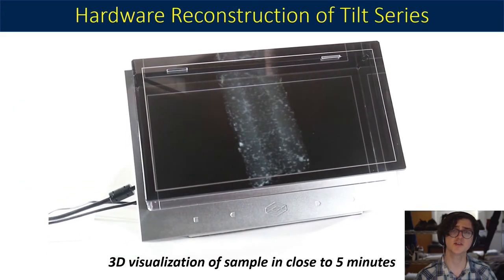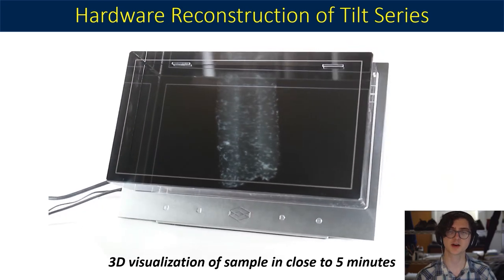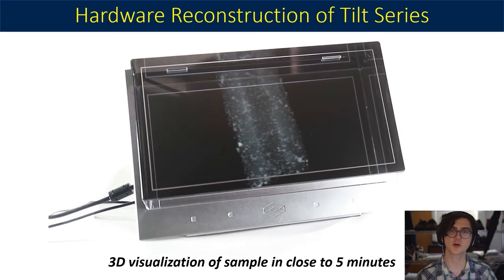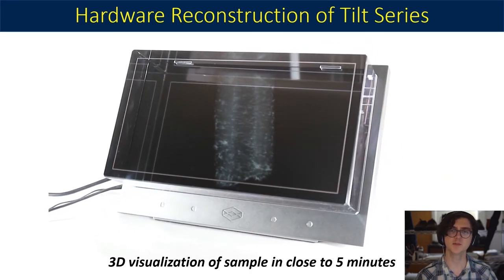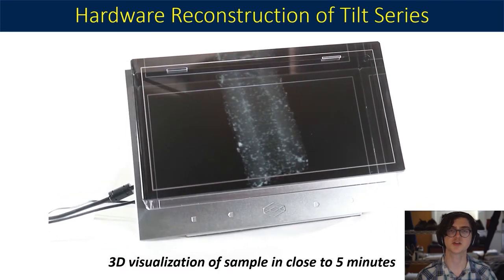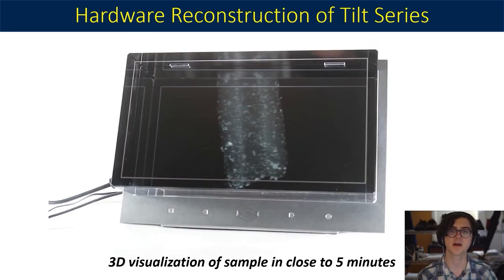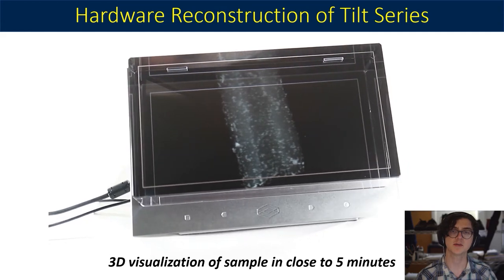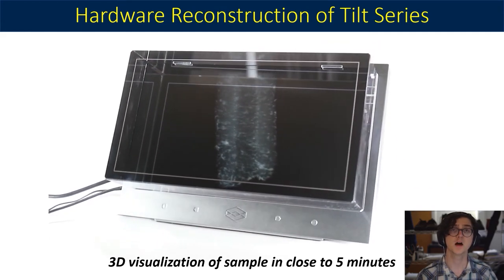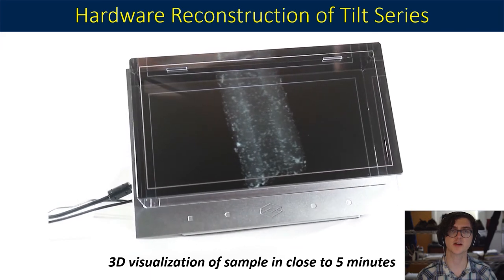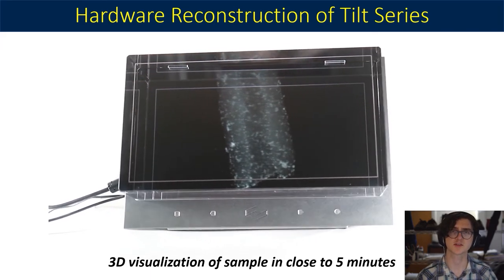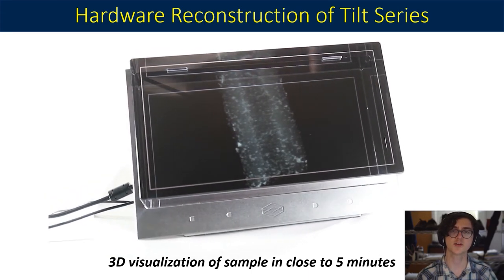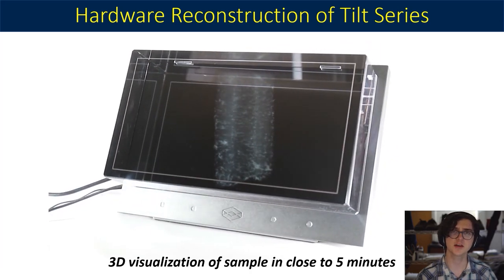As can be seen, this fix causes a convincing 3D effect. With only about 40 degrees of tilt needed, we can manually take a lower-resolution tilt series within about 5 minutes. This is because the narrow angle range avoids issues with eucentricity in traditional tomography that complicates high-tilt acquisition. This data can then be quickly adjusted and piped to the holographic display, giving a 3D visualization of the sample without the time-intensive tomography process. Of course, tomography is still necessary for true volumetric data, but this rapid visualization method via the hardware is valuable for revealing 3D structure of a material while still on the microscope, effectively giving a 3D preview.